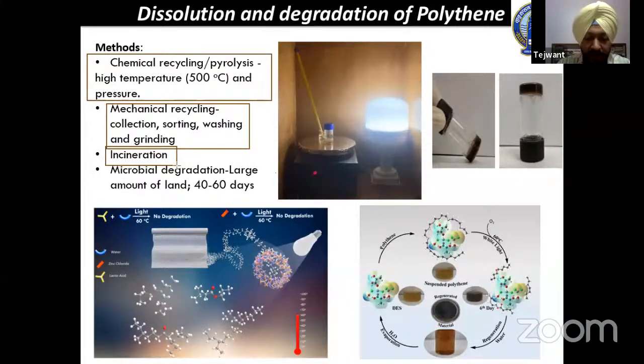Another thing which is being used is microbes, the genetically modified bacteria, which give microbial degradation of the polythene. However, in this case also, a large amount of land is required, and it takes 40 to 60 days. So we have developed a system comprising zinc chloride and lactic acid and water as a deep eutectic solvent.